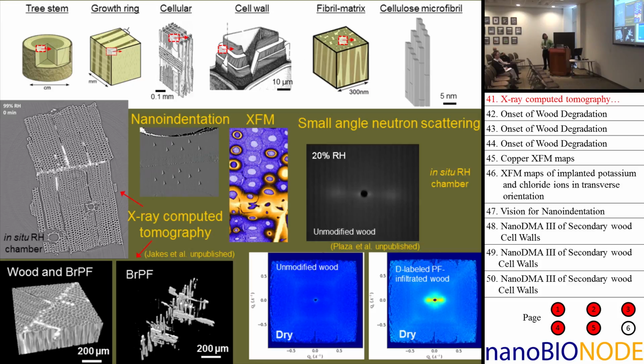In addition to that, we've also started doing small angle neutron scattering to get at what's going on down at the nanoscale. In this experiment, this is unmodified wood. And again, we built a humidity chamber to go into the neutron beamline. What you see here are these peaks, diffraction peaks that correspond to the spacing between crystalline elementary fibrils that make up the cellulose microfibril. The cellulose fibril is swelling with moisture, and the amount of swelling is about 20%, which is about twice as much as the swelling you see in bulk wood. So this is a strong indication that if you want to make a good wood adhesive, you've got to stop the swelling inside of these microfibrils.